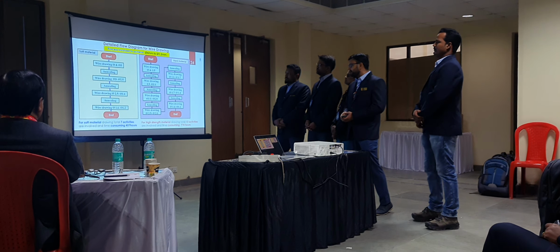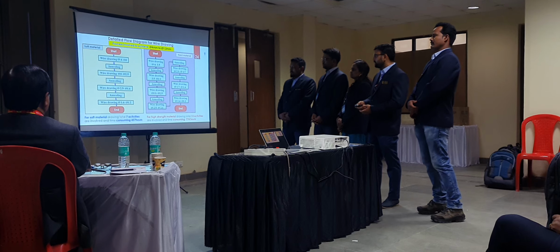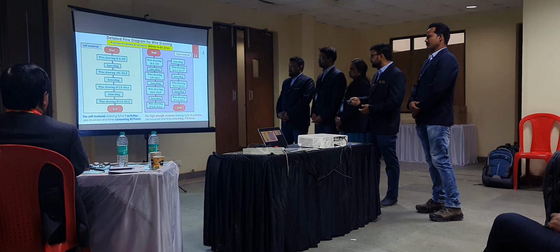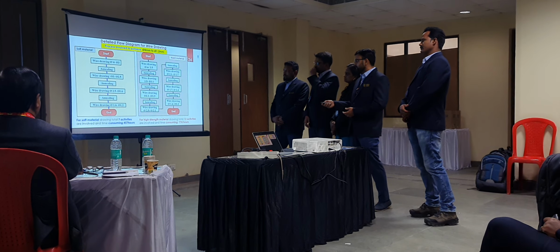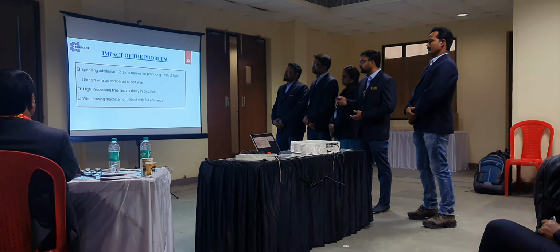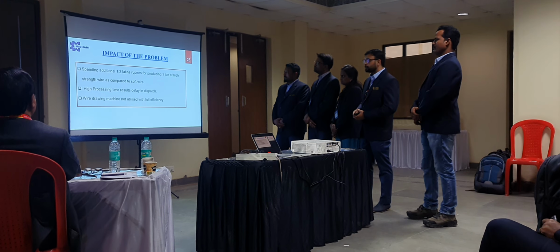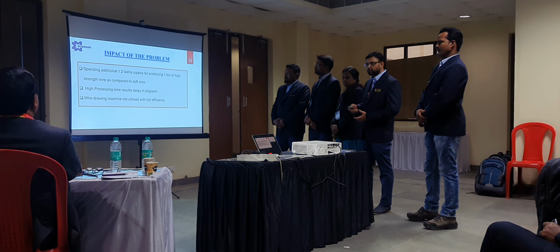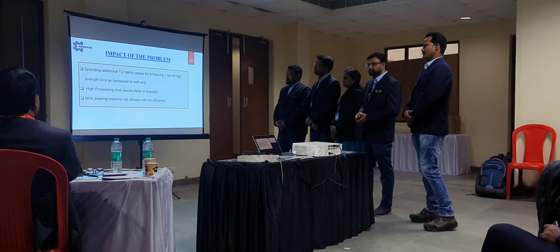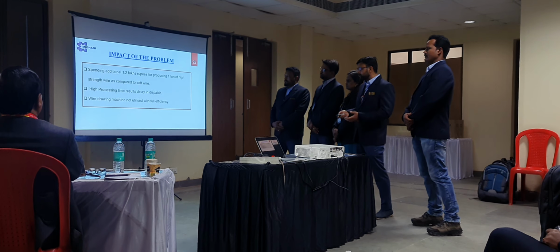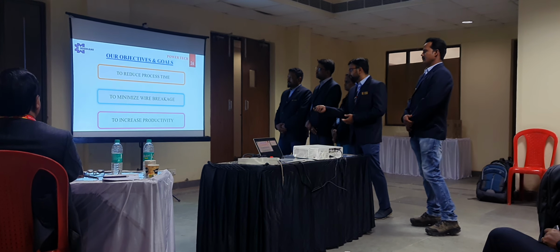For soft material, 7 activities consuming 457 hours. And for hard material it requires 13 activities with 774 hours. The impact of the problem is we have to incur an additional 1.2 lakhs of rupees for producing 1 ton of hard material as compared to soft material. Also it is hampering our dispatch activities, and we are not able to utilize our full machine efficiency.